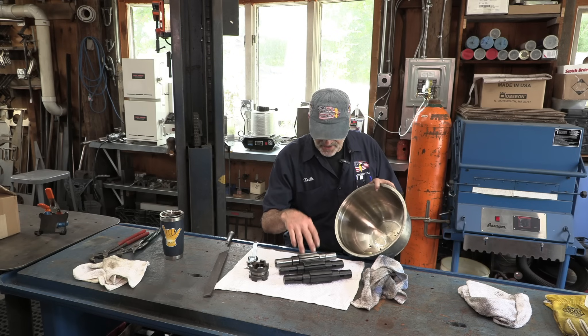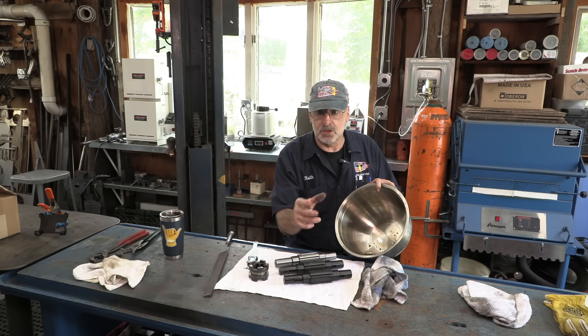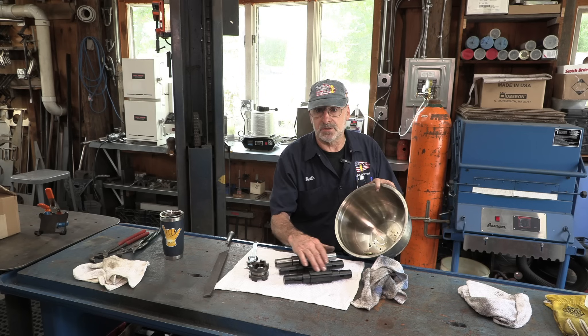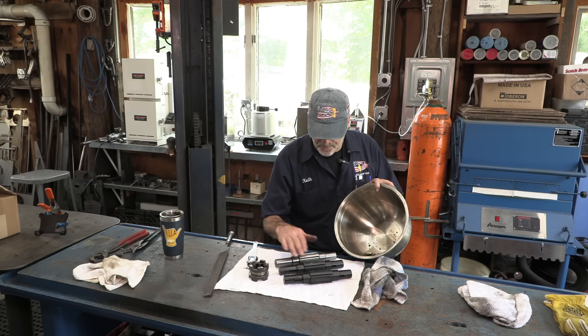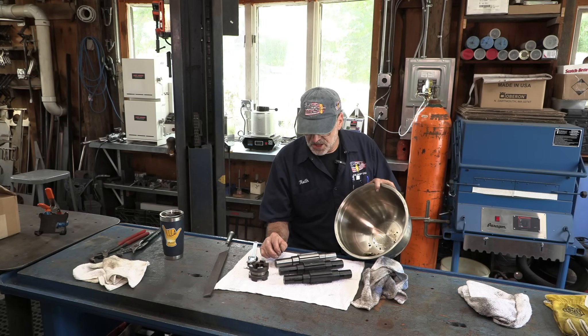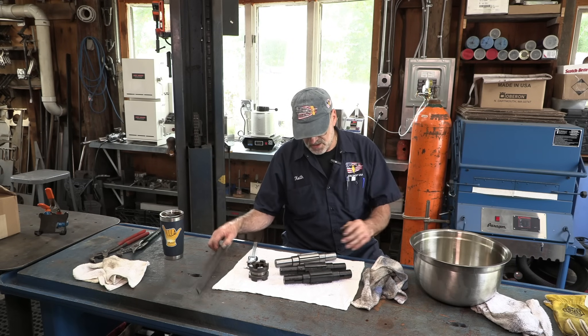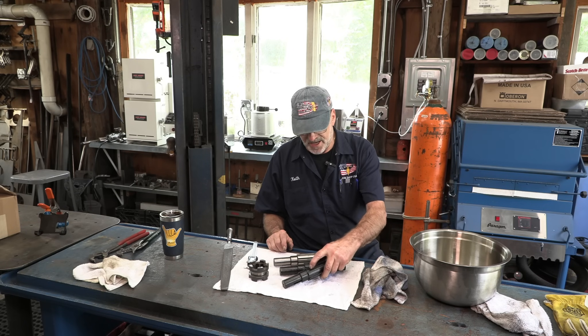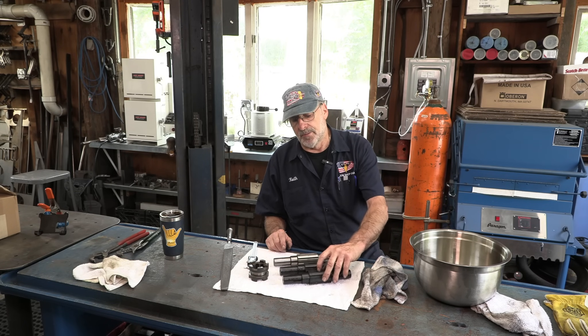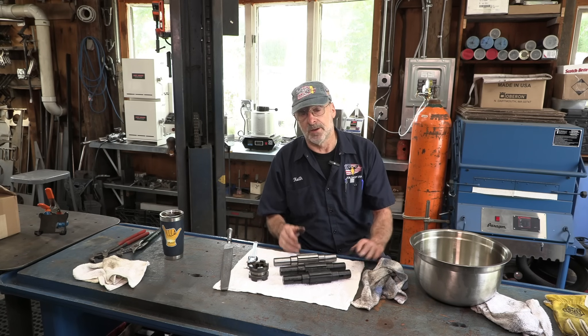It's unbelievable how thin the surface scale is. I've had some stuff come out looking black calico — shapes and chunks, surface texture through the bumps and peels. This is just pretty much black, that's it — just color. Wire brushing lineally this way did that, and then going with the machine marks around the diameters cleared it right off. Some people ask how I'm telling the difference with the file — it's the file and fingernail test. I can feel I'm actually grooving it here, but with the same pressure I can groove into the stock, I'm not grooving it on those treated shafts. That's how I come up with that determination — it's not rocket science.